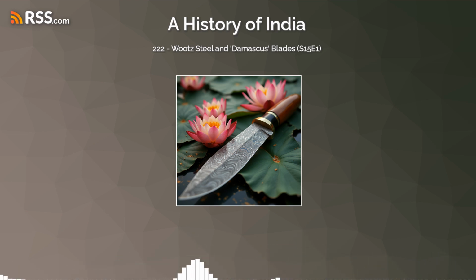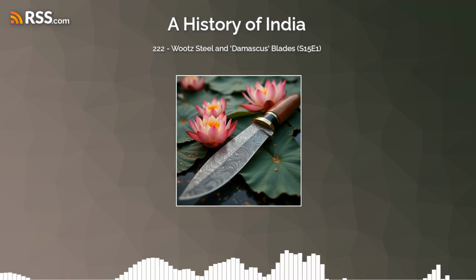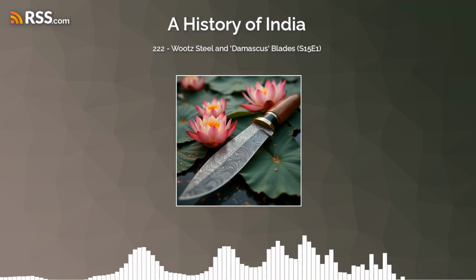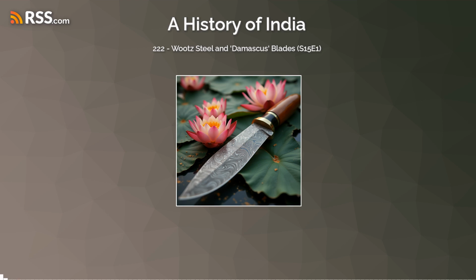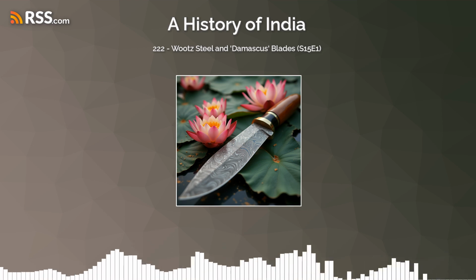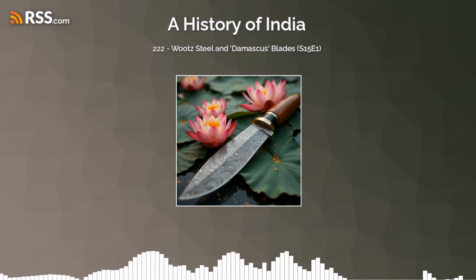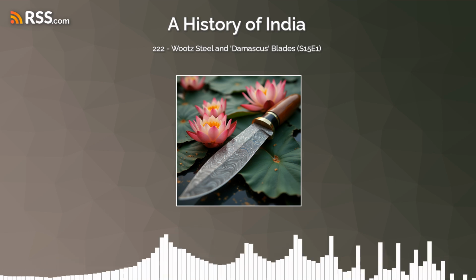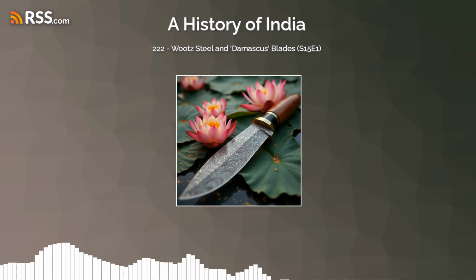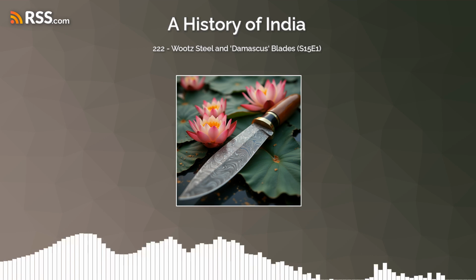These trace elements helped keep the cementite plates really thin and aligned them in parallel within the softer iron matrix. This specific structure, this alignment, was key to everything. The steel's strength, its surprising flexibility, its ability to hold that famous edge. And it was fundamental to creating the visible pattern. So getting that tiny amount right was crucial.